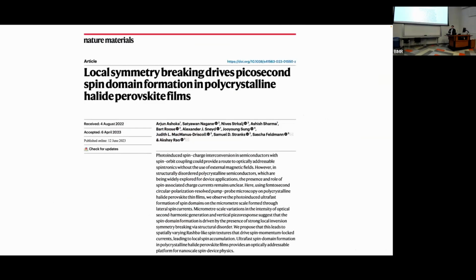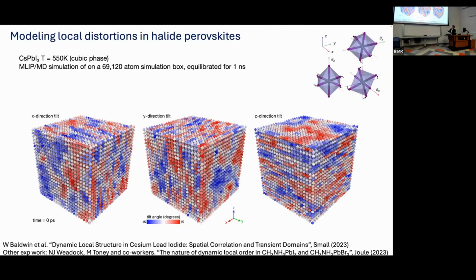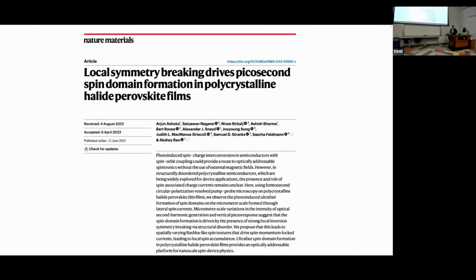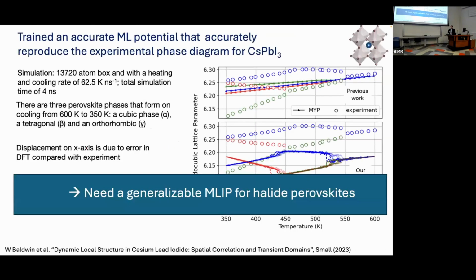And after this work, there was some work also by Mike Toney around the same summer that we published ours, which actually looked at this experimentally and reported a similar phenomenon of this dynamic local ordering in these ABX3 systems. In this case, they used organic cations instead of inorganic systems. There's also, around the same time, a paper that reported that this Rashba-Dresselhaus spin splitting event occurs in perovskites, and they related it to this local symmetry breaking. So this dynamic structure they're observing could be related to the change in electronic properties, which could lead to, for example, spin splitting. It's something that we're still investigating, exactly the relationship between these two aspects.